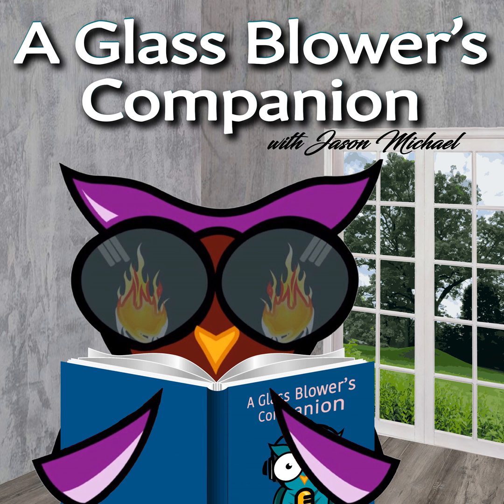Yeah, and the melting points are definitely different. Most soft glass, or the Moretti, which is a variation of the soft glass rods used for sculpture, little figures and beads, is around 850 to 900 degrees. That's the melting point where the molecular structure actually becomes hyperactive, in a sense, because glass is always active. It's just at a resting point because it's at a cold temperature. But once it gets to the melting point where it becomes active, it's around 850 to 900, where borosilicate is 1050. And the flames are around 3,000 to 4,000 degrees.